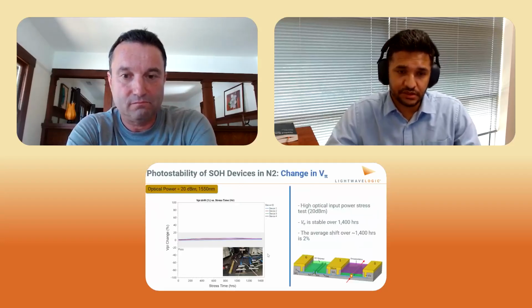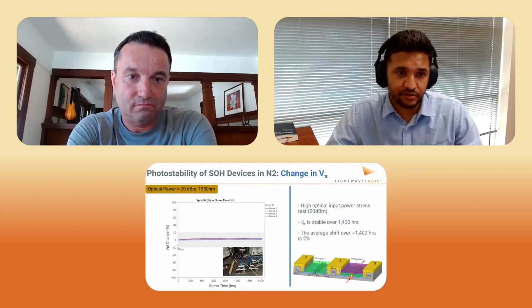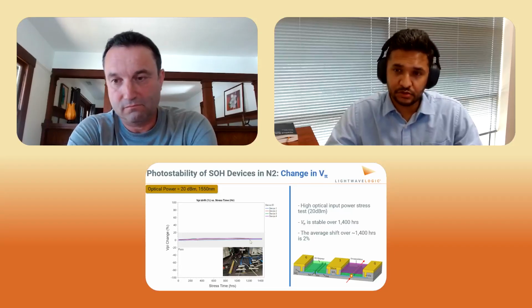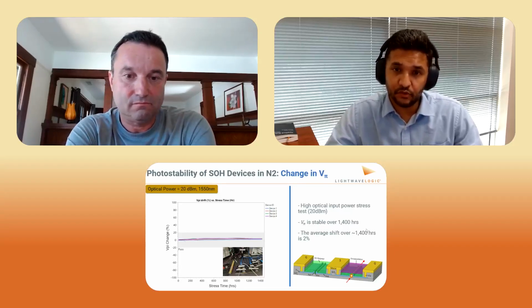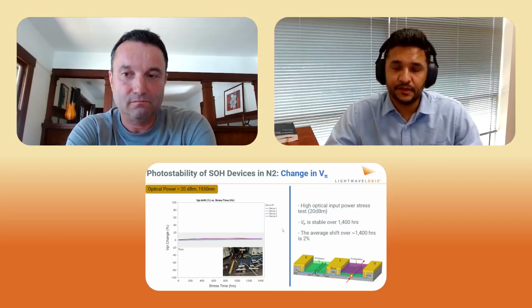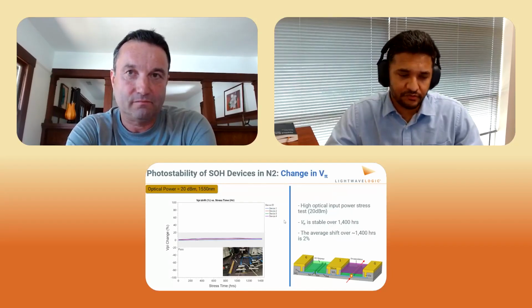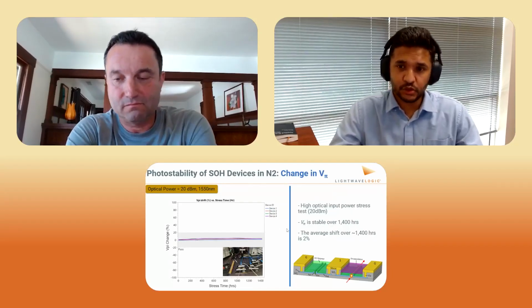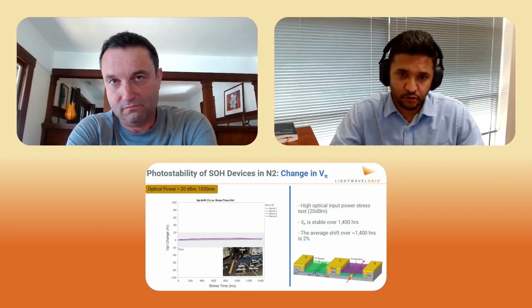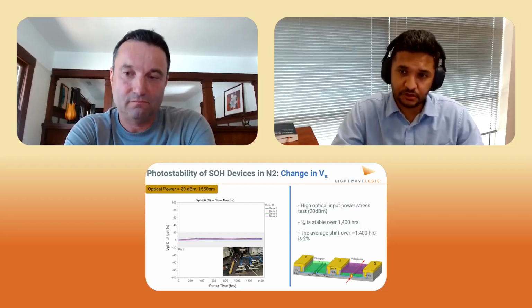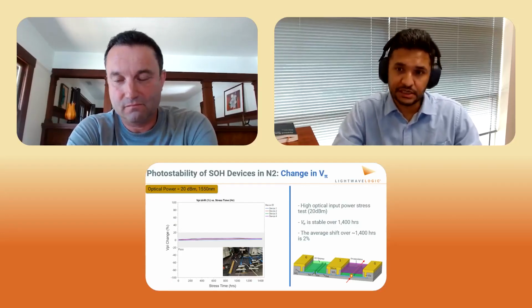And what we found is in nitrogen environment, when we put a lot of light through chromophore, there is no damage to chromophore even after 1400 hours. So yeah, in theory, we prove that if there is no oxygen present, no matter how much light you put through, the chromophore is intact.